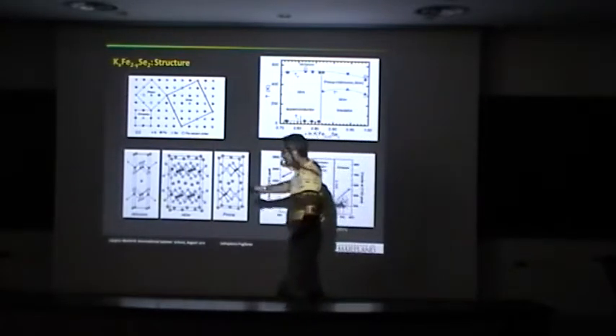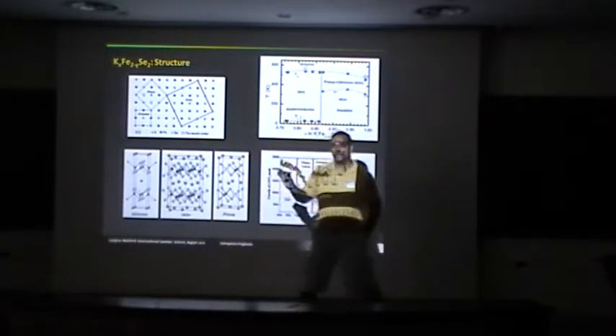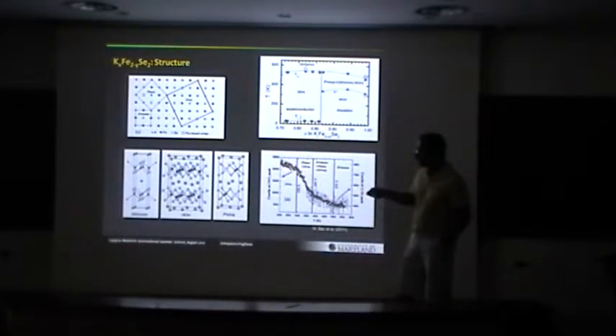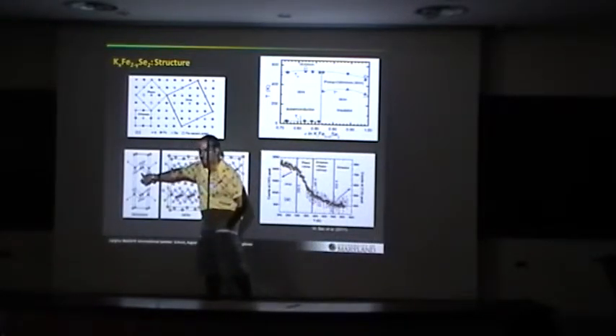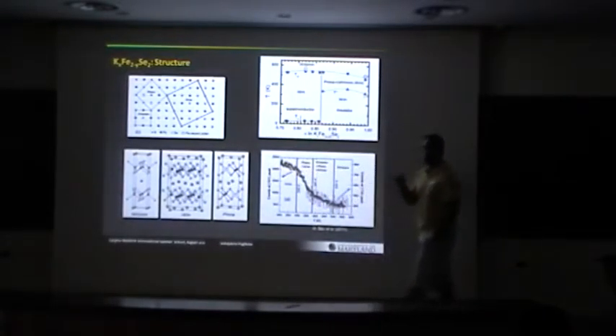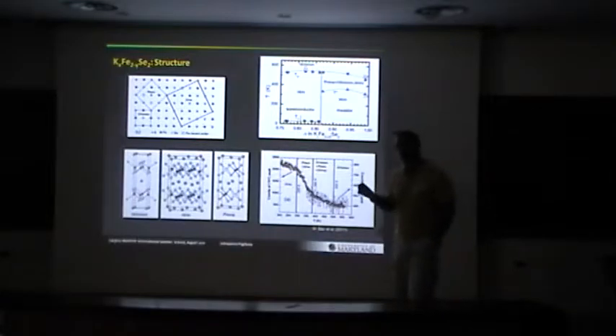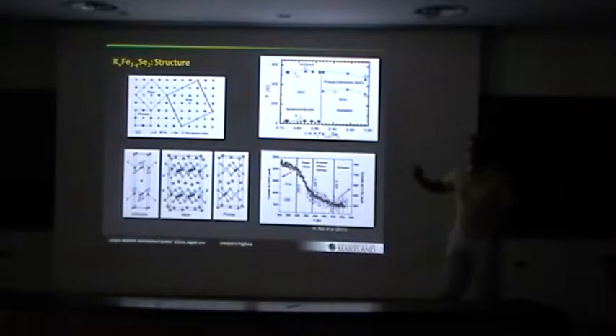Because iron selenide is basically these layers without these. In that case there is interstitial iron that I think sits here, and the amount of that varies. You can never get it to iron 1, selenium 1. It's always iron 1 plus a few percent. So that interstitial iron does play a role in the magnetic properties. But there are no iron vacancies in that system.